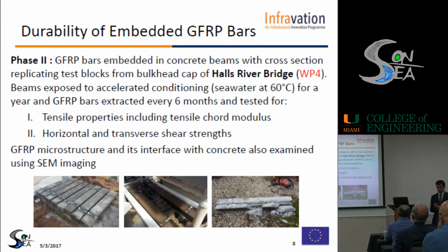Then we officially started the SEACON project in October 2015. At that time, we started casting more samples. We embedded GFRP bars in these types of beams. These beams are about 6 feet long, and the cross-section is 6 by 7.5 inches. These were supposed to be the same as the test blocks that we have at Halls River Bridge.